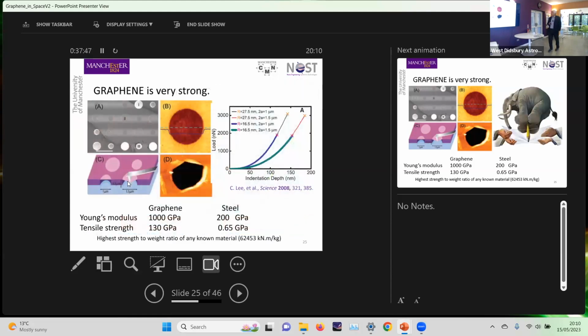So graphene is very strong. I've said that a few times now. How do we know it's very strong? Well, one of the ways is we took some of our little flakes and we put them over little holes that we'd etched into a suitable material, silicon nitride, and we took a little cantilever with a stylus on it, and we poked the surface, and we poked it hard enough so that it would rupture the surface. Now, these little cantilevers are on springs. So essentially, as we poke into the surface, the spring deflects, and we can measure that deflection accurately to within a subatomic distance. So we can measure that very, very precisely. And that tells us what force we're putting on the surface, because we know the spring constant.